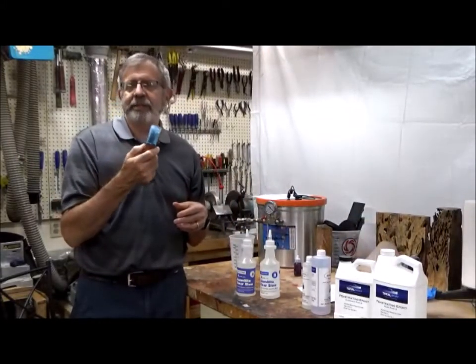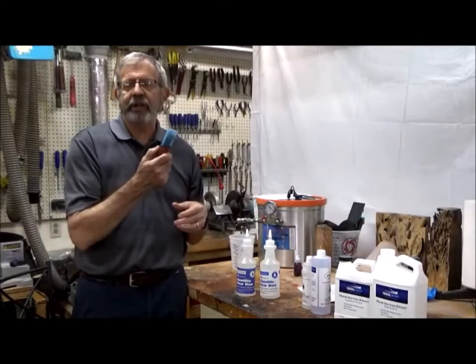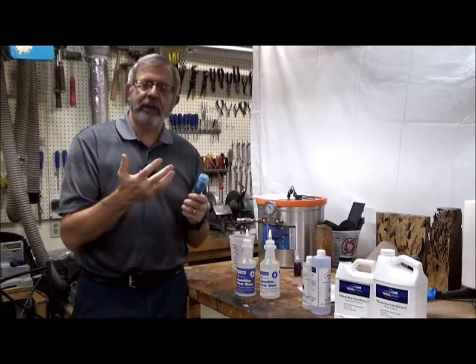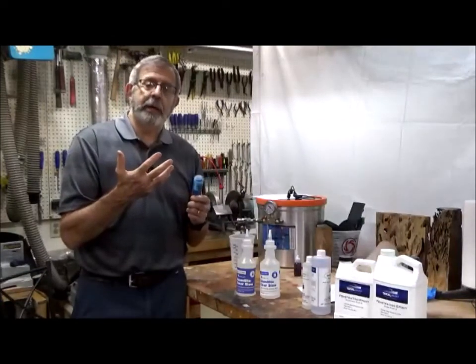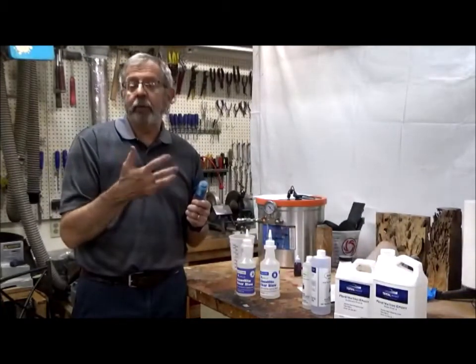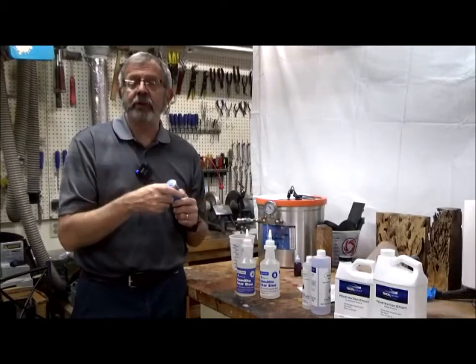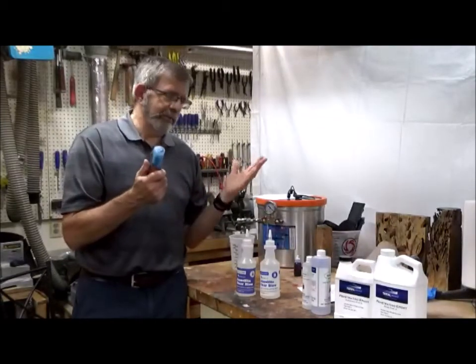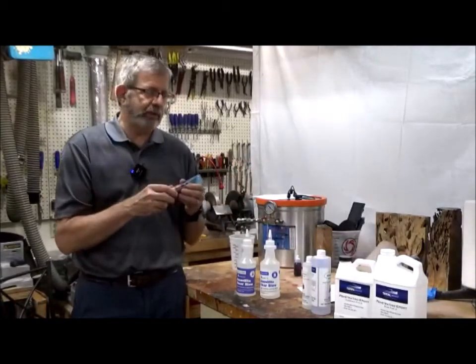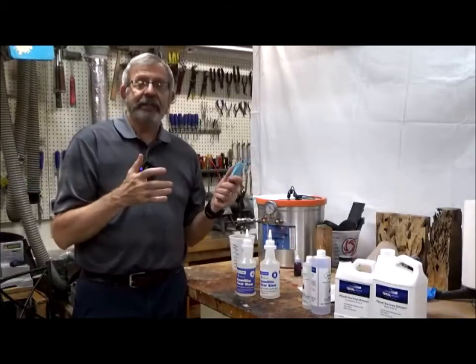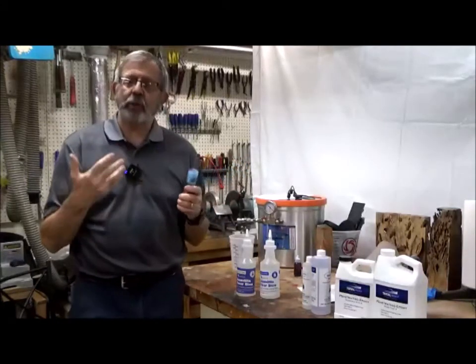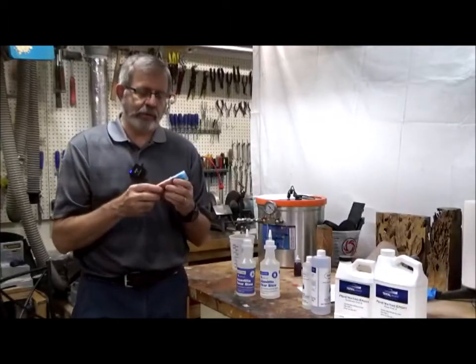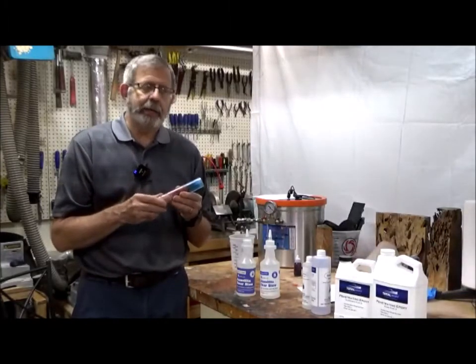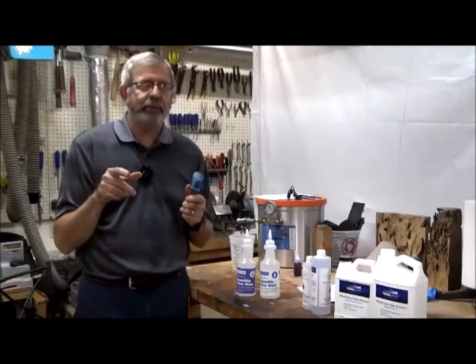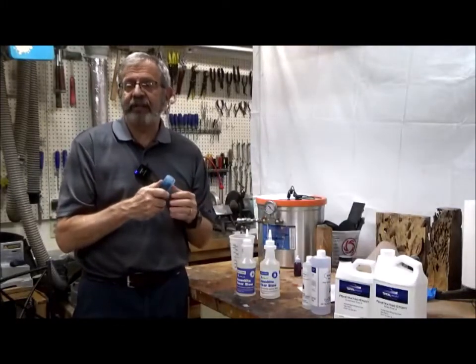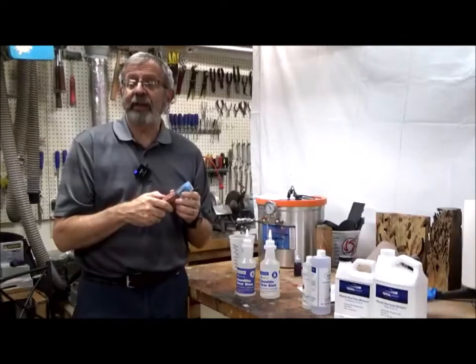Even if I use the slow, it's got 12 minutes of open time, and within 2 hours you can demold it and turn it. So very quickly you can use it. The problem is that because it sets so quickly, it generates a lot of heat. It's an exothermic reaction. And when we show some of the pieces later, you'll see that because of that, you really can't pour it very thick.